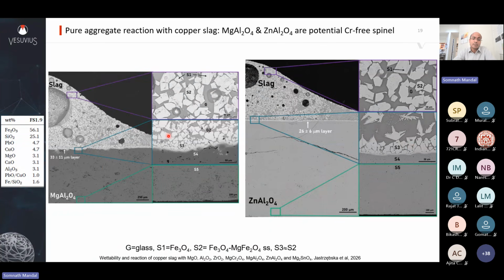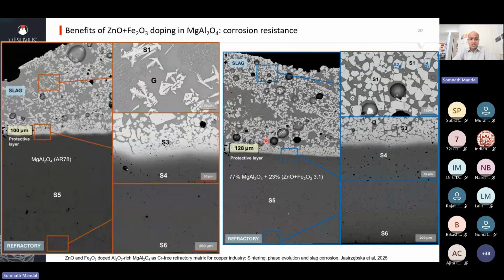Now you see the candidate magnesium aluminate bonding phase as having very low reactivity, and there is a little bit of solid solution formation which is beneficial to form a passivation layer. This is due to the magnetite going into solid solution with your spinel phase. And a similar observation you see in zinc aluminate, just that there's a little bit of difference in the layer formation, the protective layer formation. So, as I said earlier, zinc and iron doping into magnesium aluminate spinel is showing benefit, and it tends to give you a higher slag viscosity, which is beneficial. Not only that, when you look at the interface, other than this, the phases are exactly the same, but at the interface you see a little bit thicker protective layer, and this layer formation is beneficial in terms of slag corrosion.